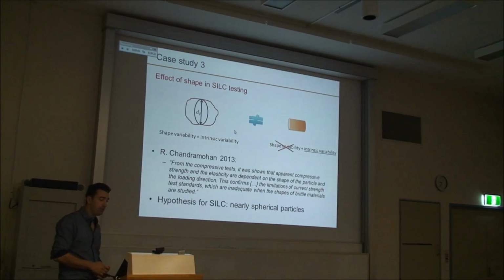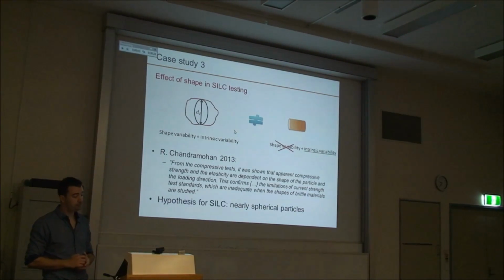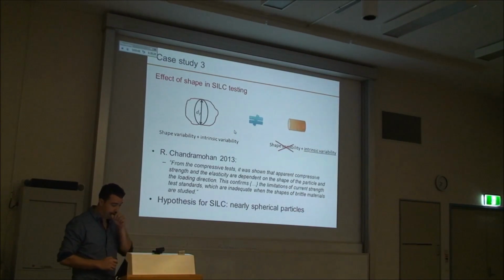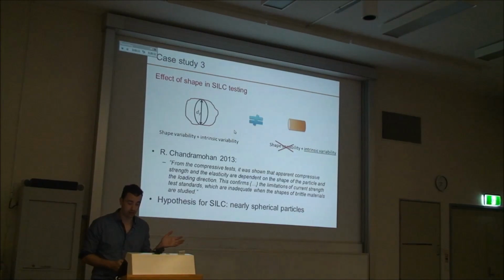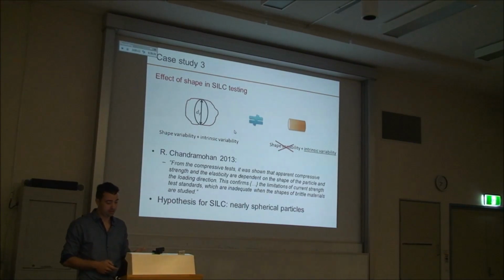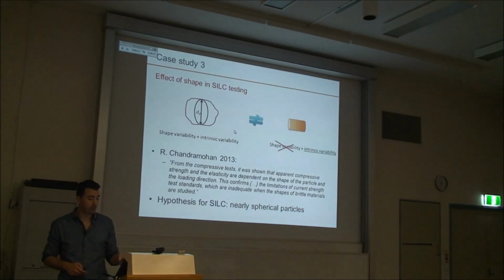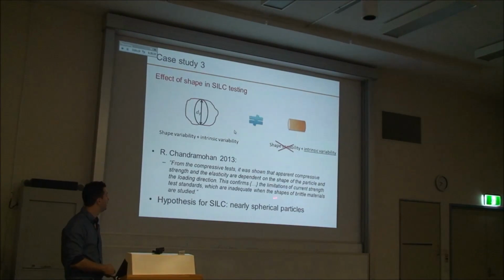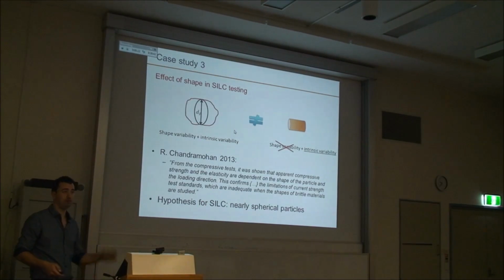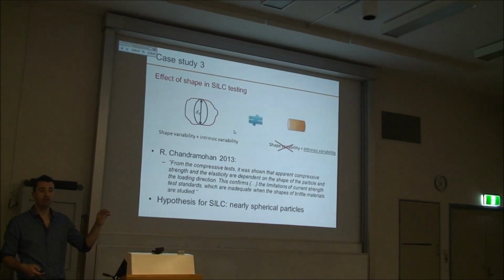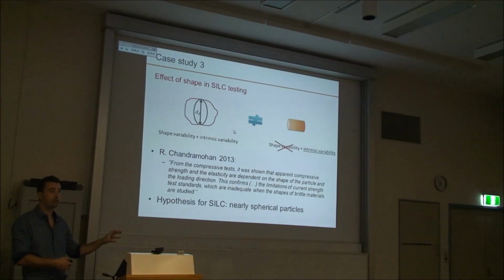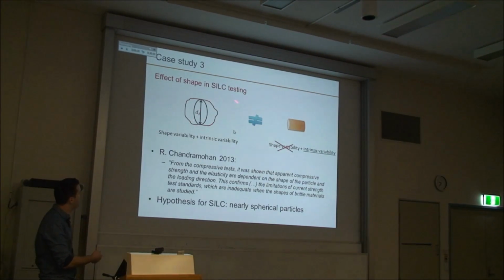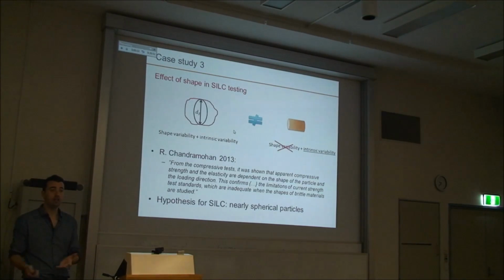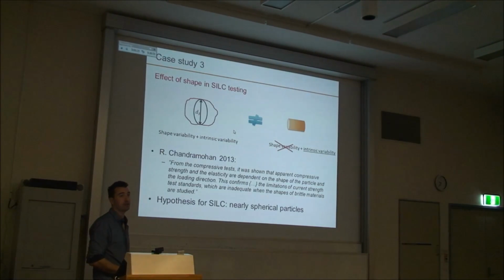But Chandramohan in his thesis said that from the compressive test it was shown that apparent compressive strength and elasticity are dependent on the shape of the particles and the loading conditions. The limitation of the current strength test standards, which are inadequate when the shapes of brittle materials are studied. And SILC, well, didn't miss that. Spot on. The shape was at the heart of the hypothesis used for all the calculations. So basically, when you switch from this shape to this shape, all the calculations I've shown before fall apart. Okay? They're not valid anymore.